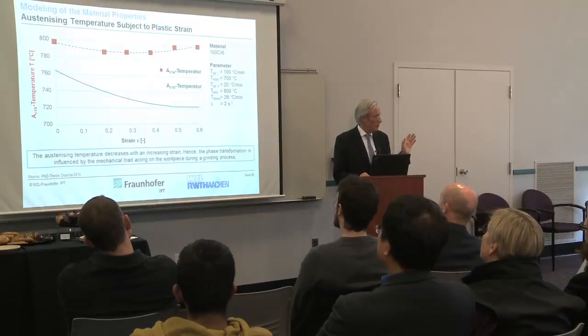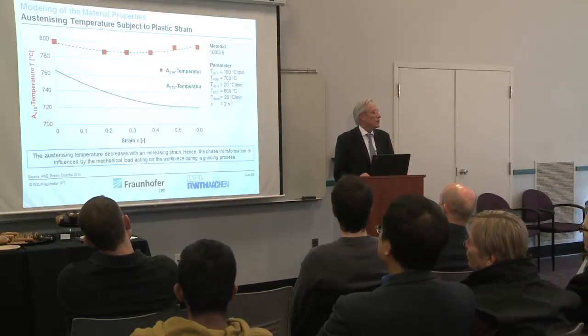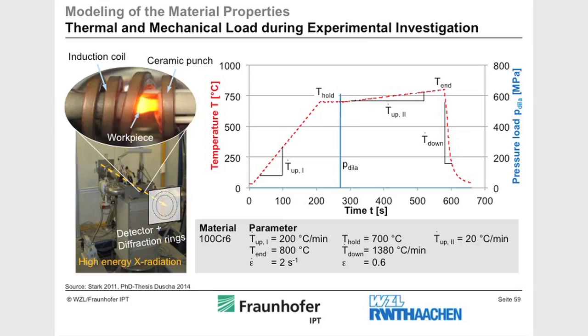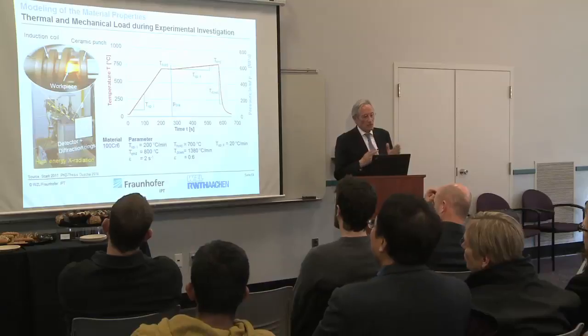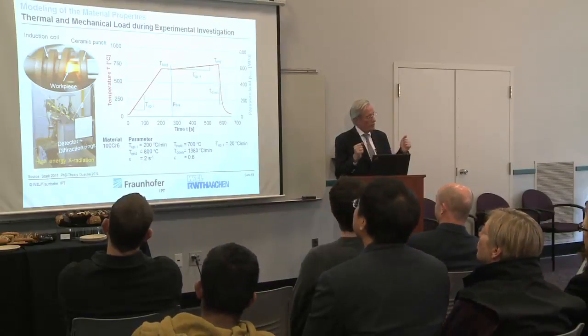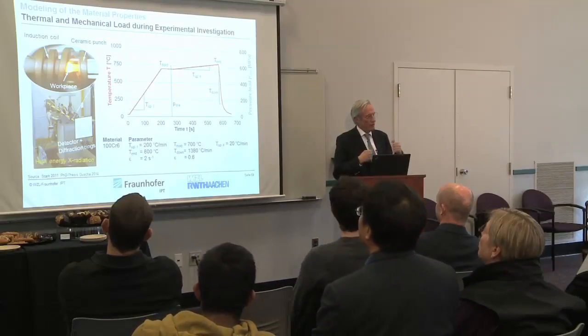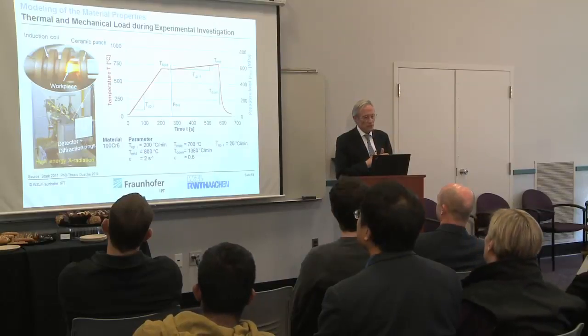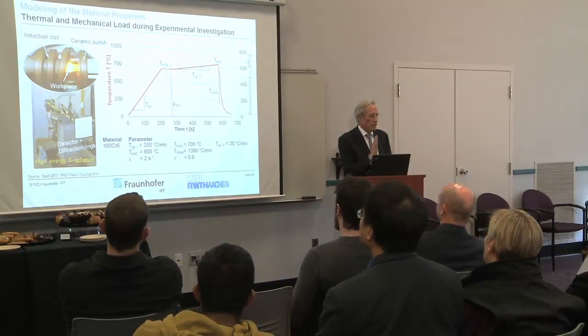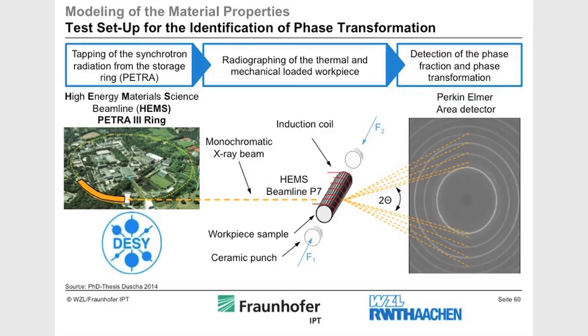So what is important, because at the bottom line, you would like to know the phases which you have in the material. So that has to be done by experiments. How can you do these experiments? So we made little specimens. You see a coil, ceramic punches, and then in between we have this material. We heat it up, put it under pressure, so we have pressure and heat, according to the real grinding conditions, and then we send X-rays through that material. And according to the phases that we have, we see refractions of the X-ray, what is called Bragg's circles. So we see these patterns, and material scientists really can analyze what it is.